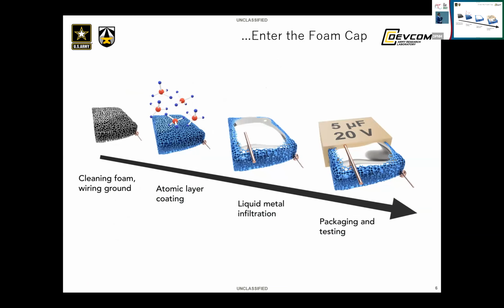So going through abbreviated fabrication steps, start with an off-the-shelf nickel metal foam and carefully thread a ground wire to it. This is something I would do at home during COVID. And then carefully grow an atomic layer thin film on top, then infiltrate this foam with liquid metal and add your counter electrode. And then this is the step that maybe we never quite got to. So let's talk about the atomic layer coating itself, because that's where most of the challenges lie.